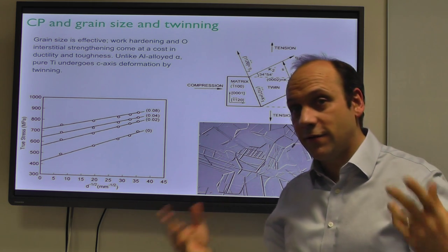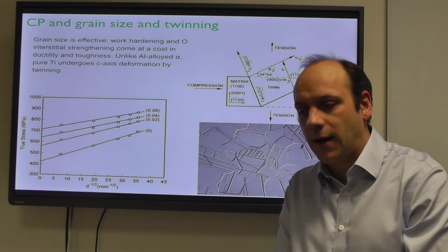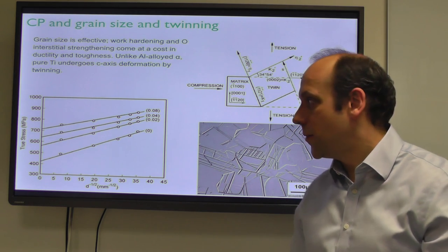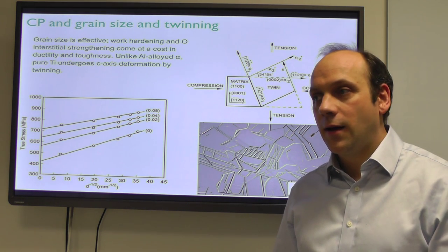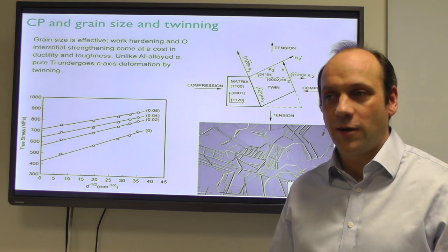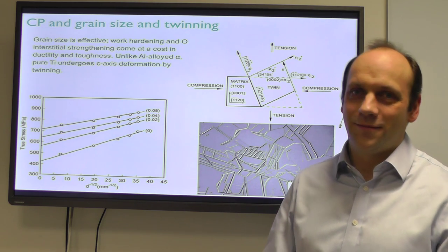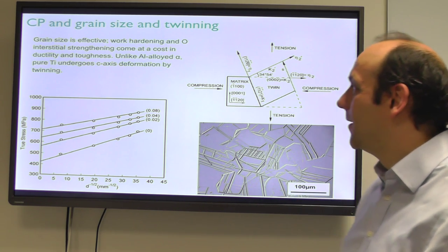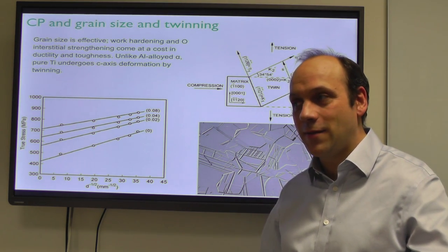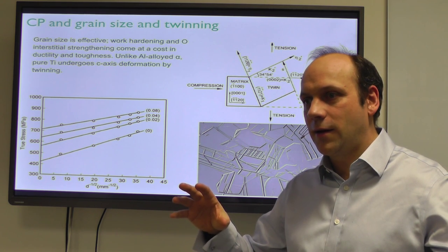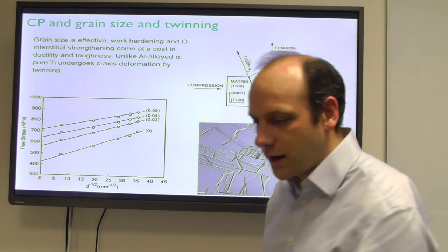And that gives you a bit of plastic relaxation. It also gives you some subdivision of the grain and some work hardening, so that tends to be a desirable thing. The only problem is it tends to exhaust. The maximum strain, if you fully twinned all of the material, would be something like 8%, so it doesn't give you very much strain. By the time you get to 20 or so percent strain, 30% strain in total, you start to exhaust the twinning mechanism, and then you run out of work hardening, and you neck and you die. That's CP titanium, as I say, primarily there for corrosion resistance in static applications. It's also used in things like heat exchanger tubes, hot air systems, that sort of thing, in aircraft.